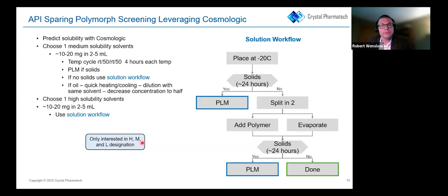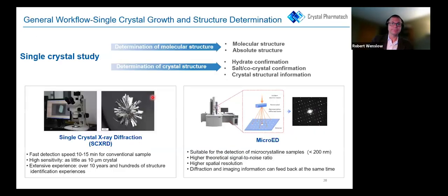And then I want to use medium solubility here. Why medium? I want enough solubility so that I can get supersaturation, but I don't want to lose all my material, right? So if I get solids, I want them to be able to turn over. So you need at least 2 to 3 milligrams per mL solubility to get rapid turnover in a 24-hour time frame. But I don't want to lose all my material. And so using the in silico can really help you towards that.